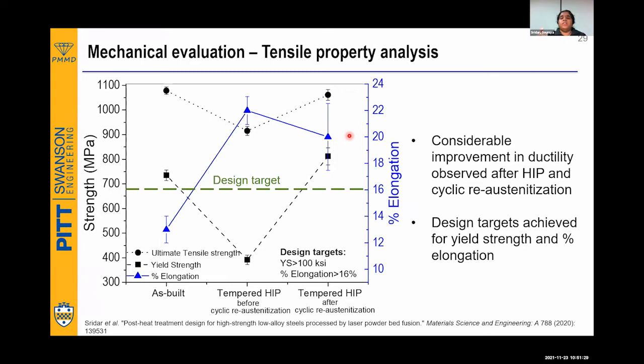But if we are getting a complete build without any cracks, the main advantage why we could do this is that first, we didn't have cracks. Only the porosity was the problem, and that we tackled using HIP and cyclic reaustenization. If we have porosity, it need not be thrown into the trash can or dumped. You can still work on it and make the properties improve.